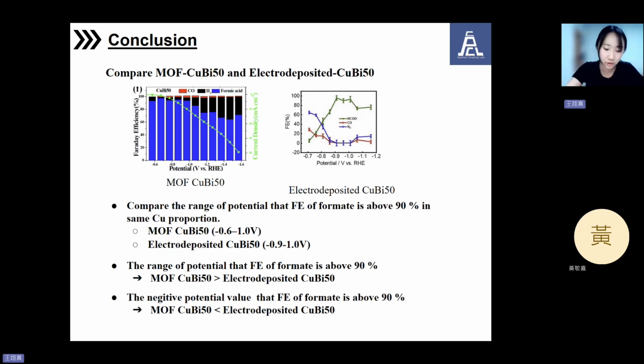To conclude our presentation, we compare two catalysts with the same copper and bismuth ratio, the MOF CuBi 50 and the deposited CuBi 50. As we can see from the chart, the MOF CuBi 50 shown on the left maintains a formate FE of about 90% across a broad potential range from -0.6 to -1 V. Meanwhile, the electrode-deposited CuBi 50 shown on the right only achieves over 90% FE in a narrow range.